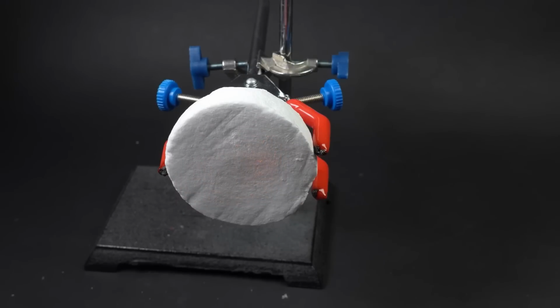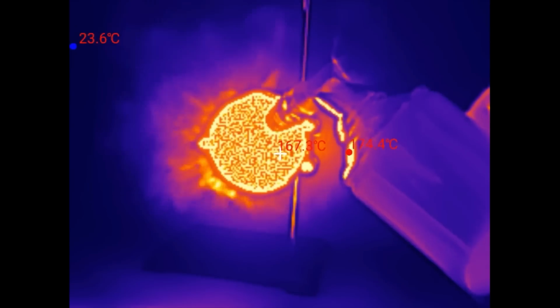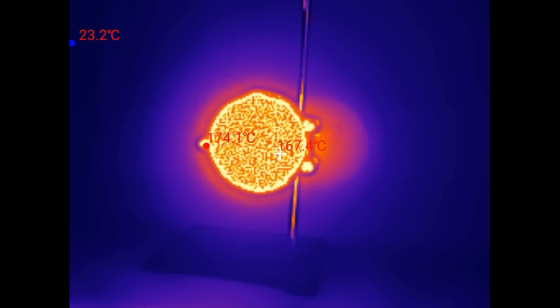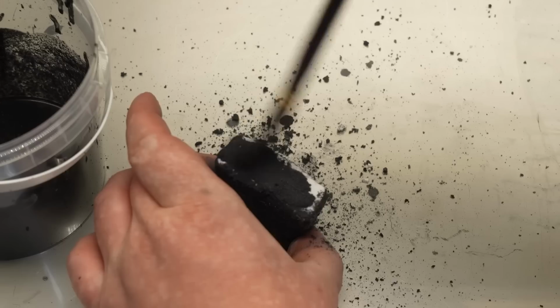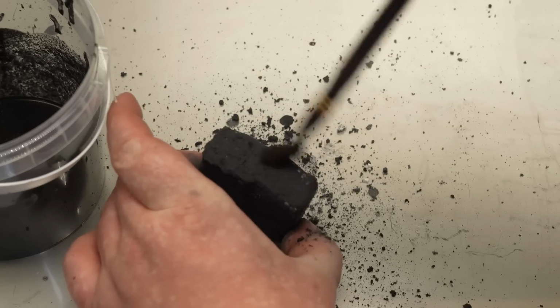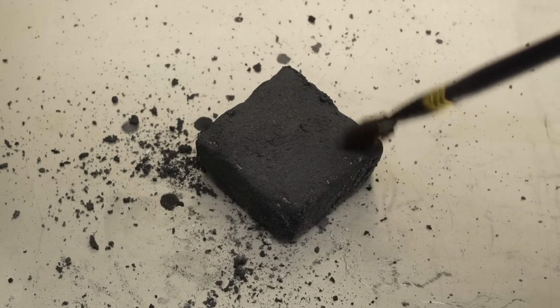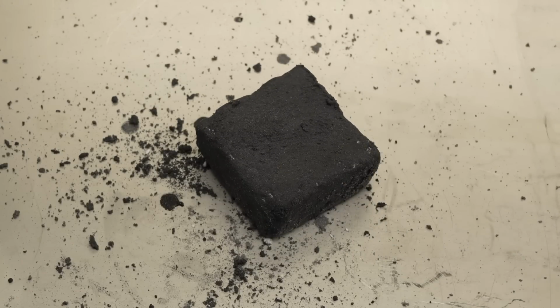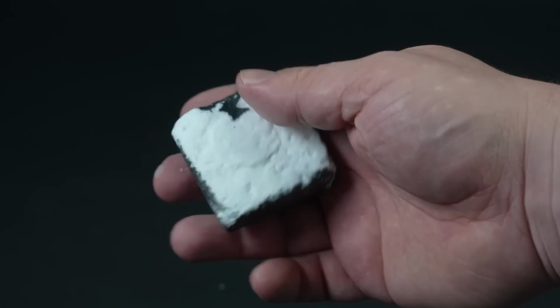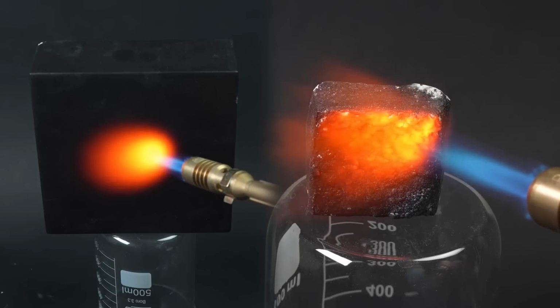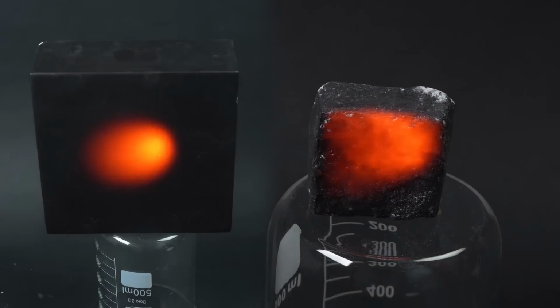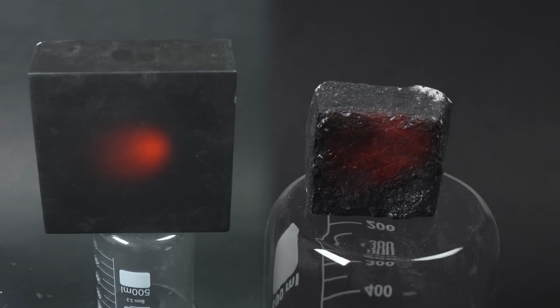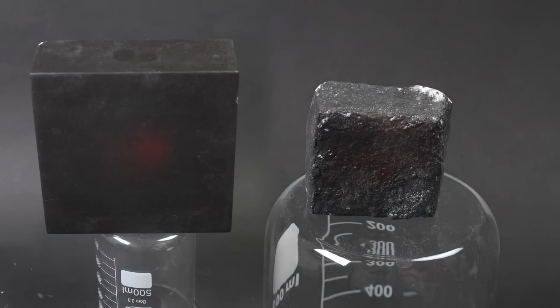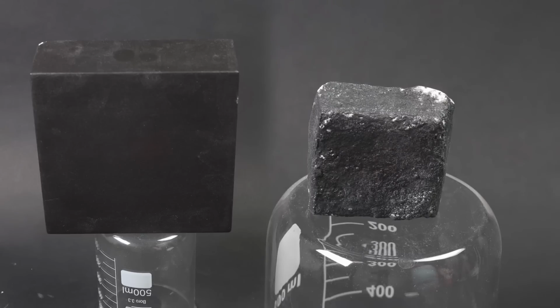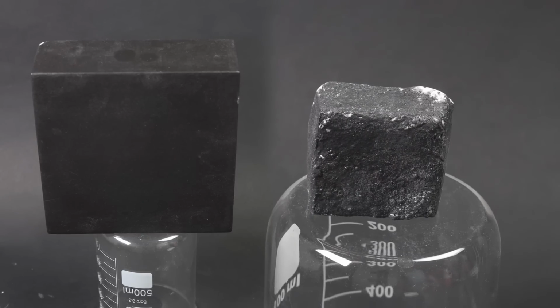The same tile, only white, cools down a bit more slowly, although due to its greater thickness it does not heat up as much. In addition to the round heat-resistant tile, I decided to make a small square one, also painting it with a black coating, after which I baked it in the oven. If we compare how my homemade tiles behave compared to the original from Buran, the difference is not particularly noticeable. The black coating re-emits residual heat very well, while the quartz filling prevents heat from penetrating deeply into such thermal protection.